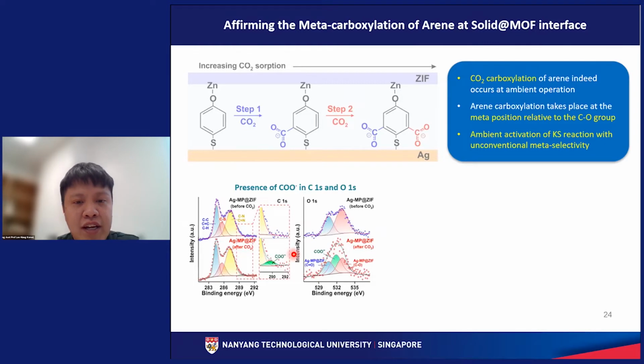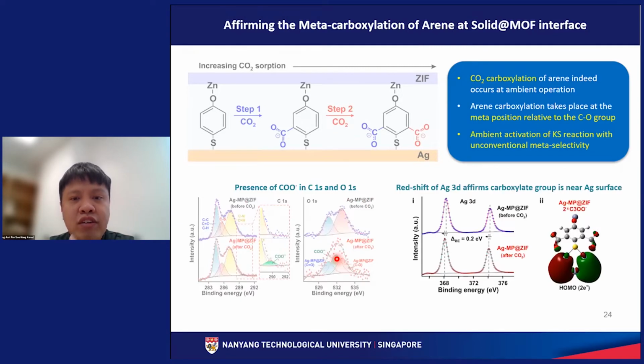Okay, so similarly in our O1s XPS test, we are able to identify the presence of carboxylate oxygen around here, in between the two peaks over here. So in short, initially it started out with only two peaks, the blue and the red. But after CO2 flow, there is an additional peak evolved, and this green peak over here corresponds to our carboxylate chemical environment. So next, how do we confirm that carboxylation indeed occurs at the meta position?